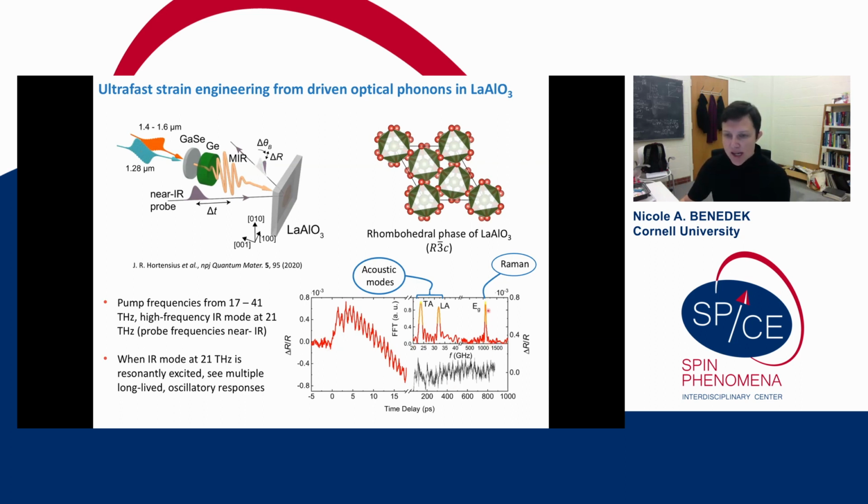This 1.1 terahertz oscillation was assigned to a Raman mode with Eg symmetry. Its response is strongly temperature dependent, and it has a lifetime of about 20 picoseconds, just based on the reflectivity data. And then these lower frequency responses are assigned to acoustic modes, and they live for much longer, up to 1,000 picoseconds.